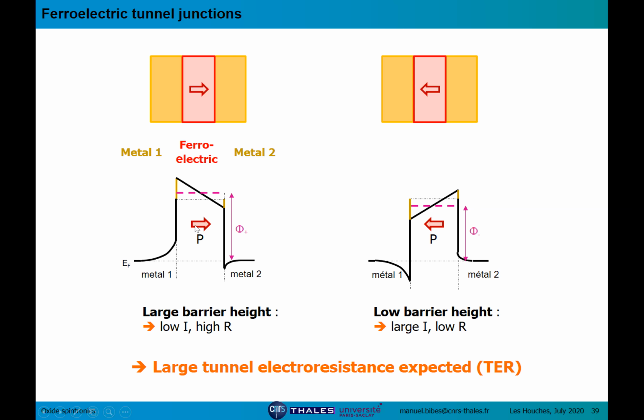So basically, in these devices, you expect to modulate the value of the average barrier height when you switch the polarization direction with an electric field. And because, again, the barrier height comes as an exponential factor into the tunneling current equation, as you switch, you expect to have a large change of resistance, and this is called tunnel electroresistance.